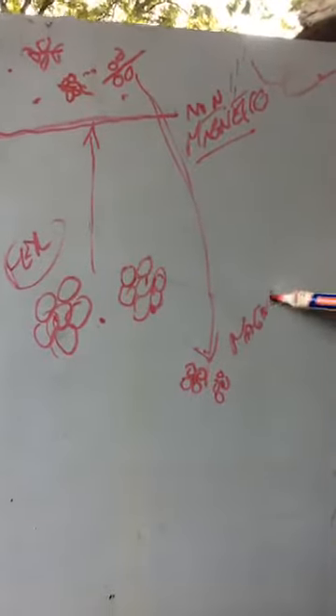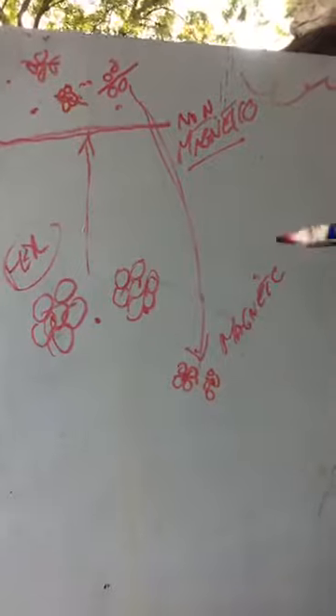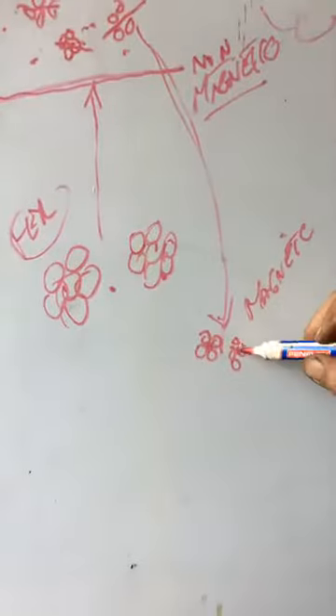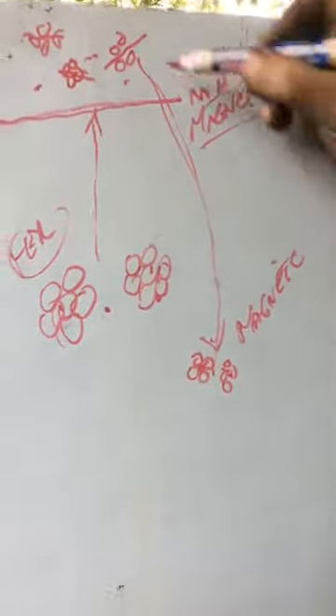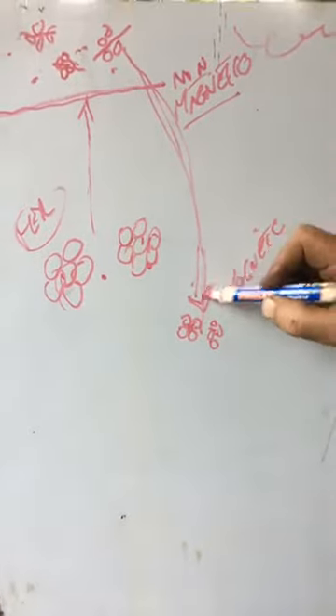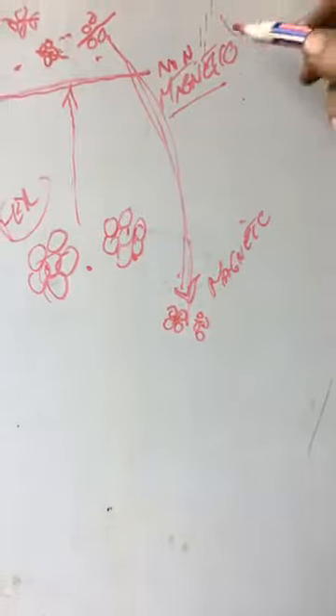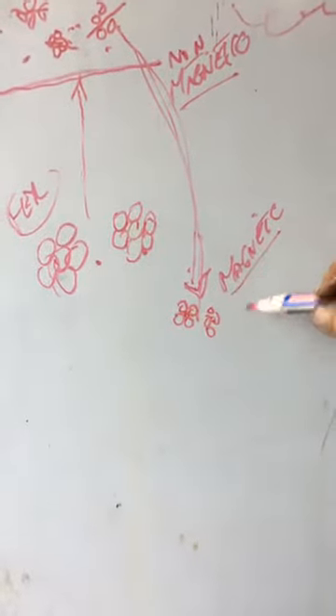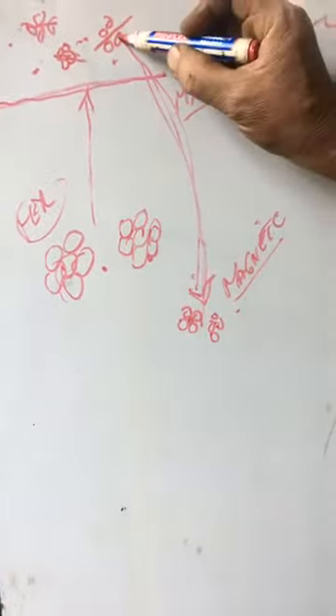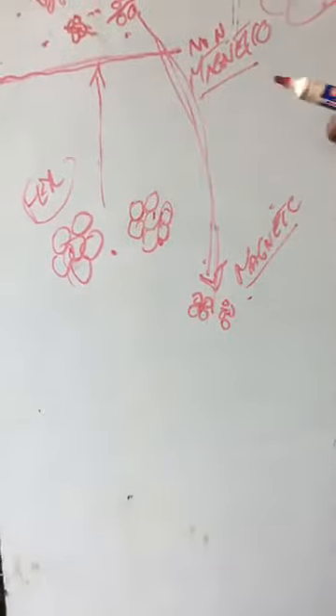It goes back to magnetic. So it does not stay non-magnetic. As it cools down, it goes back to magnetic. But key is to try and retain that grain size. To cool it down fast enough, you need to have the right quenching oil. Alright, so it's magnetic martensite. So yeah, it's magnetic. It's called martensite. It's called austenite when it's non-magnetic.